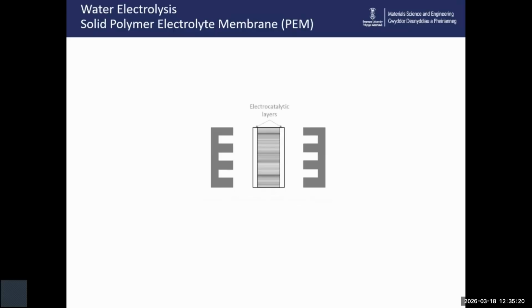The PEM is coated with a porous electrocatalytic layer on each side. Typically, carbon platinum nanoparticles on the side that will become the cathode, and porous iridium on the side that will become the anode. The electrocatalytic layers are coated with porous current collectors.